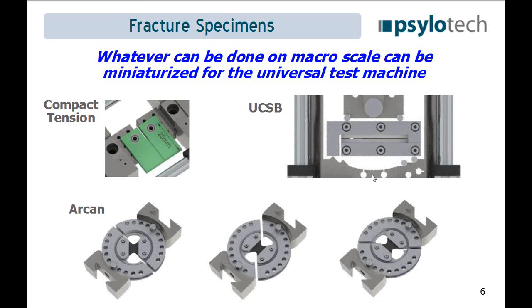Here I just show a few examples. There's a compact tension test, probably the most recognizable fracture mechanics test. There's grips for Arcan specimens, which of course will give you shear, so mode 2, mode 1 types of fracture, or mixed mode in a pretty easy way by simply rotating the grips around and installing them into the system. This is another sample that I did my PhD thesis on, which is this UCSB sample, a mixed mode sample, and in this case it was for interfacial fracture toughness of an adhesive joint. But this list could go on and on. Like I say, anything you can do on a large scale, you can do on a small scale.